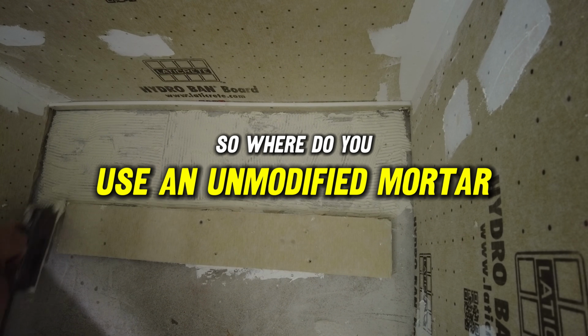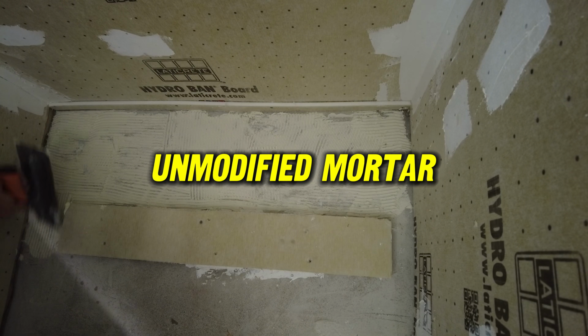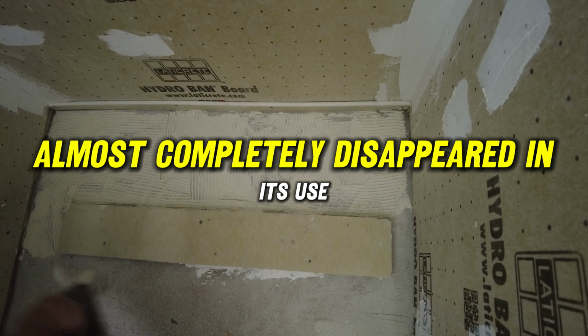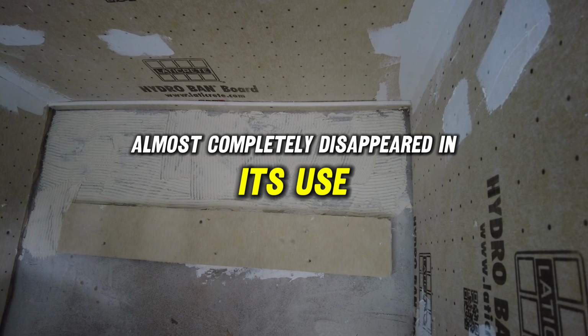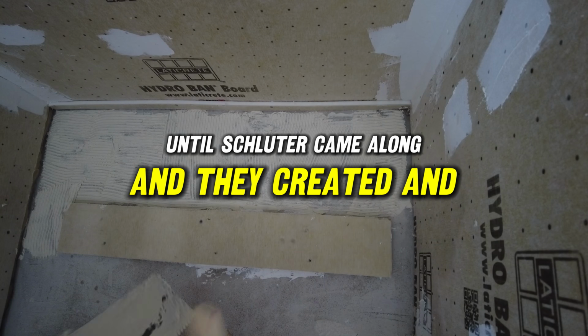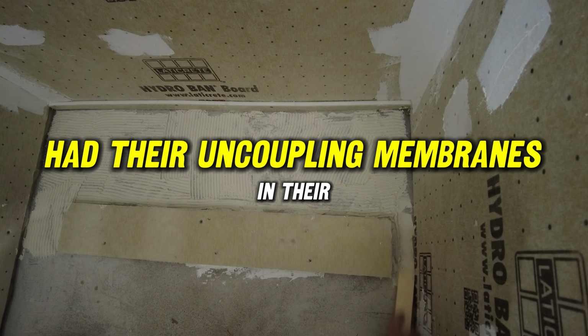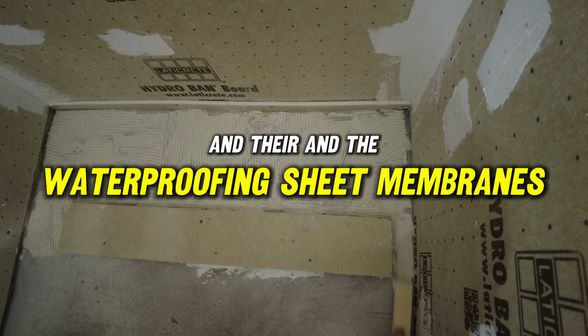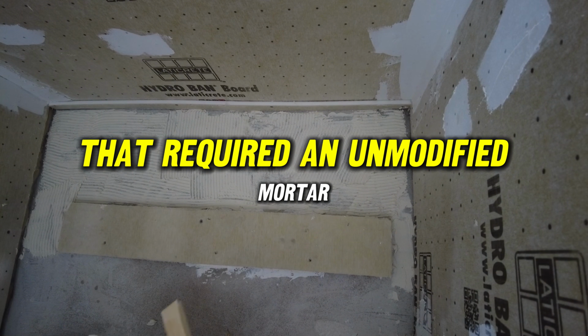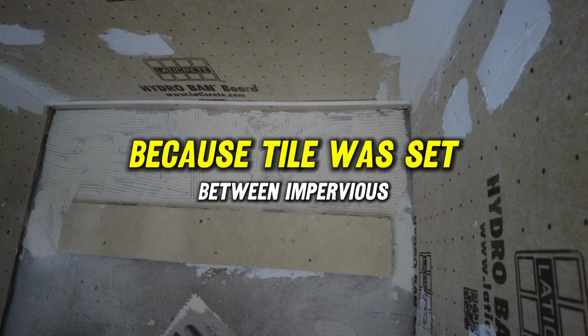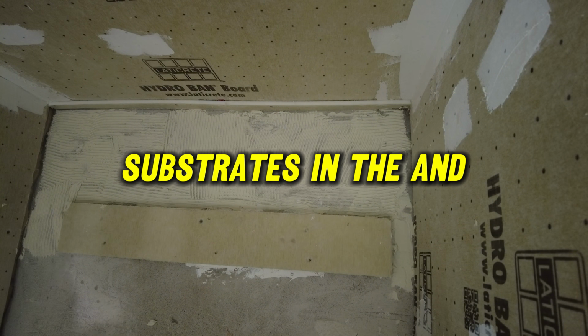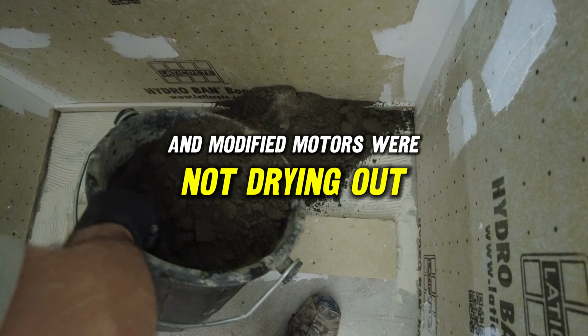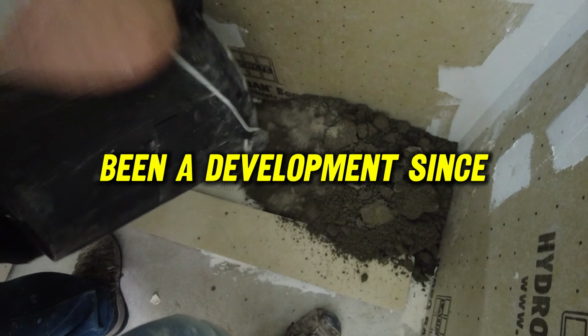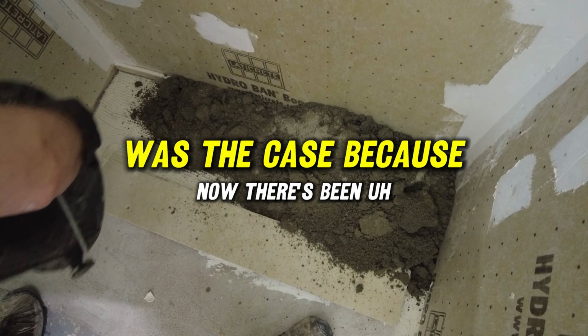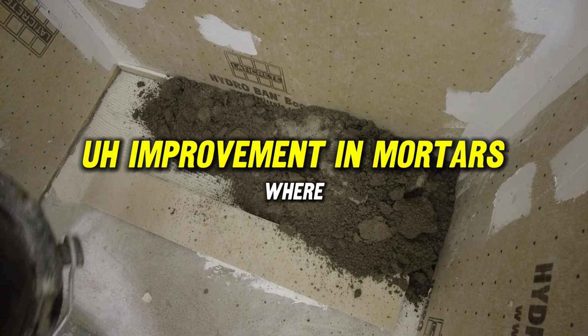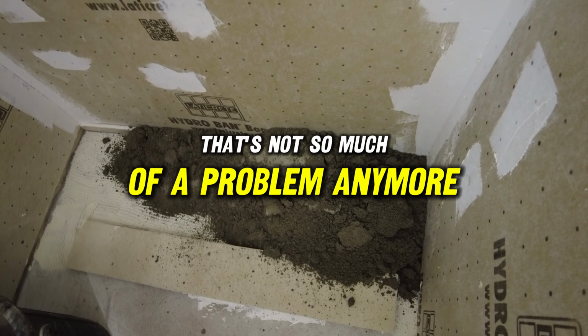So where do you use an unmodified mortar? Well, unmodified mortar almost completely disappeared in its use until Schluter came along and they had their uncoupling membranes and the waterproofing sheet membranes that required an unmodified mortar, because tile was set between impervious substrates and the modified mortars weren't drying out. Now there's been a development since, so that's not so much of a problem anymore.